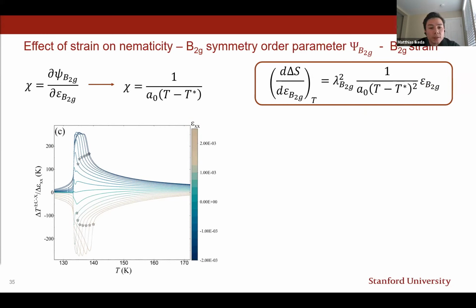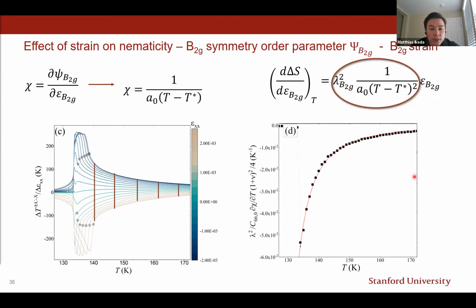And what we can find is shown in the figure on the right-hand side. We arrive at the black data points, and the red line is simply a 1 over (T minus T star) squared fit. So it is obvious from the data that for parent barium iron arsenide, we indeed are in a situation where the nematic susceptibility follows almost perfectly Curie-Weiss temperature dependence.